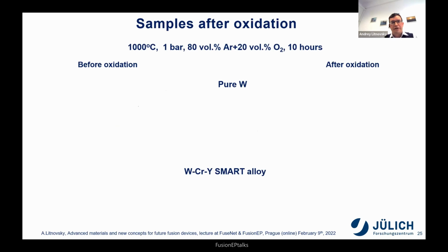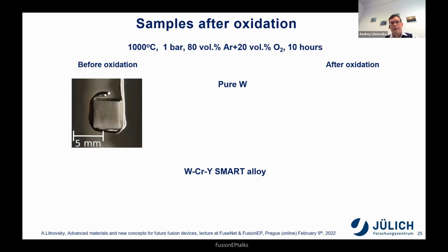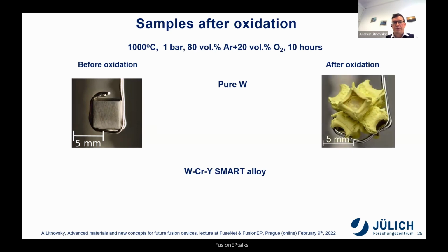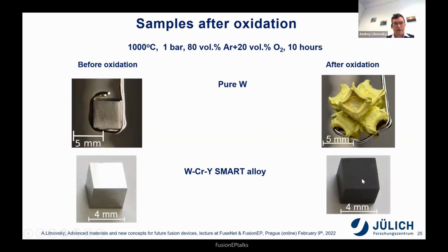Of course, since you see it in the numbers, it is also nice to see how it looks in reality. These are the results of only 10 hours of exposure of these smart alloys in the air-containing atmosphere at 1000 degrees C, at atmospheric pressure. So you see a nice and shiny tungsten sample, and this is what happens after the 10 hours. It completely loses the shape, it continues to oxidize and even opens a hook, as you see here. What will happen with the smart alloy, initially so shiny? It will just become black. And it completely preserves the shape. If you scratch this a little bit, it will be shiny, because there are only a couple of micrometers of this protecting layer. So nothing happens with it. So they indeed feature quite impressive resistance to oxidation.